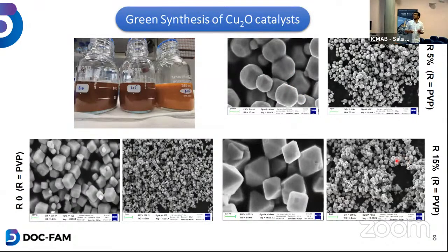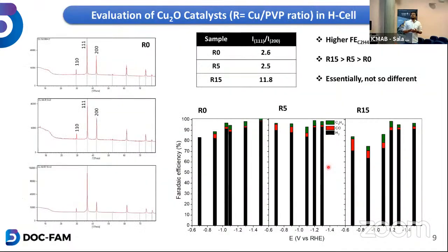And then when I have R15, when I even further increase the content of PVP, I have even more amounts of multifaceted ones. This has both 111 and 200 phases of copper, which is quite good for ethylene production, as stated. So initially, I have done the analysis in the conventional H-cell.